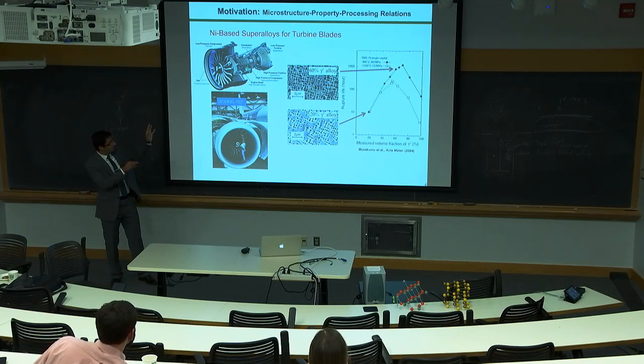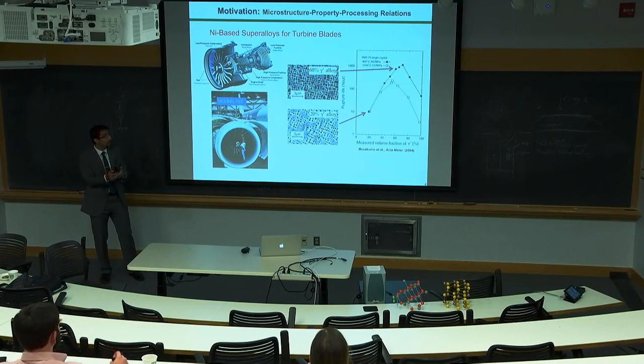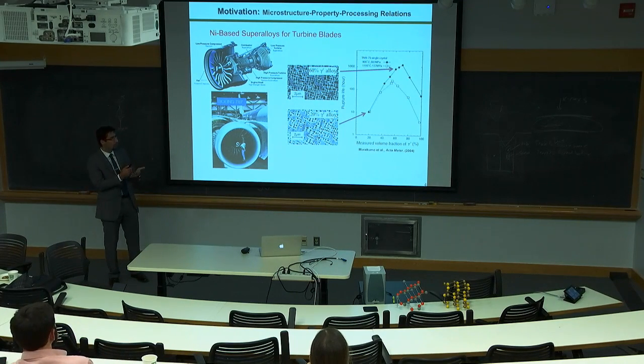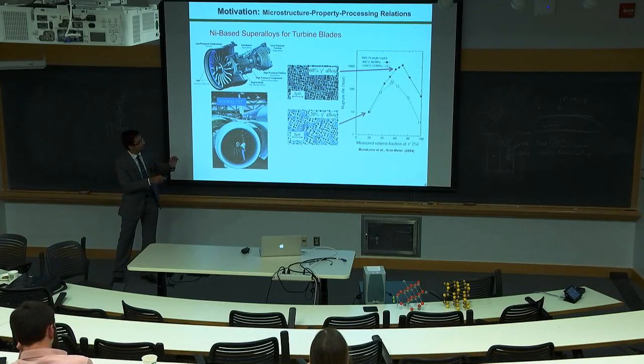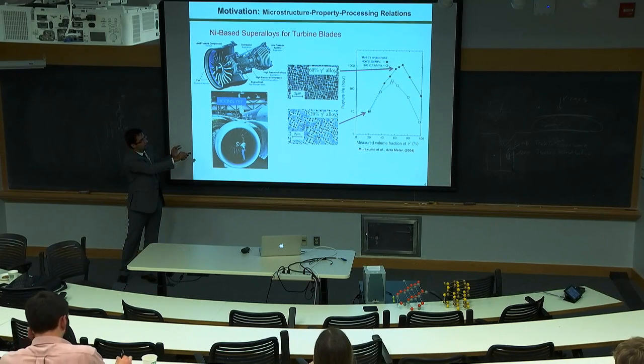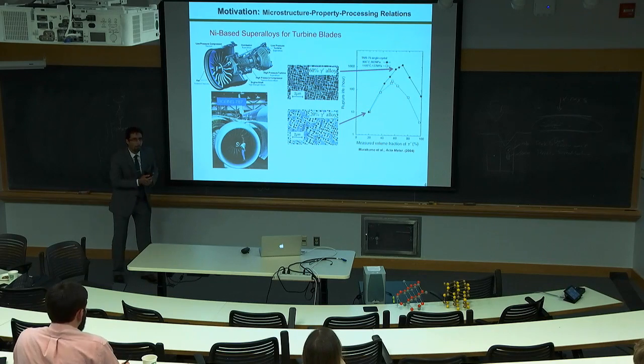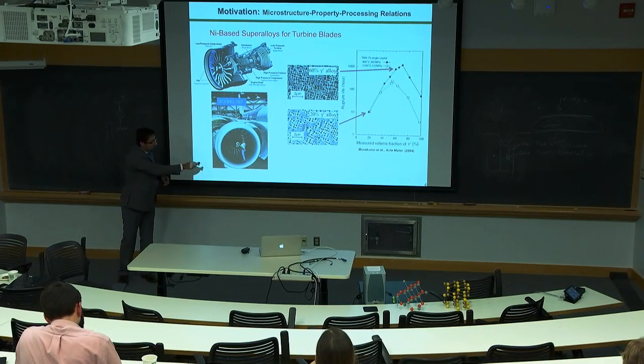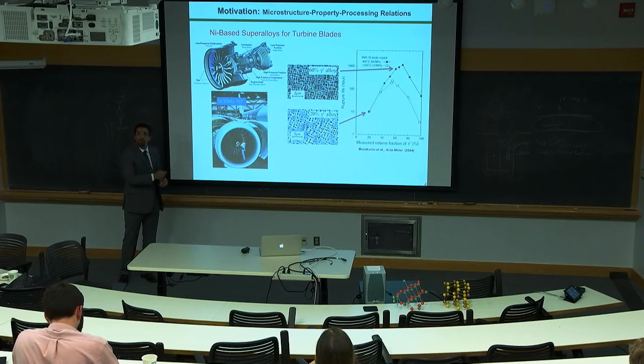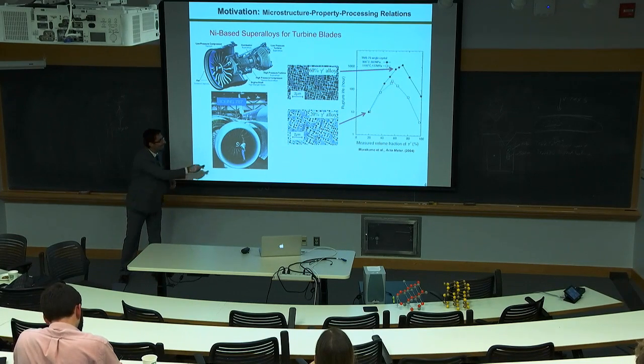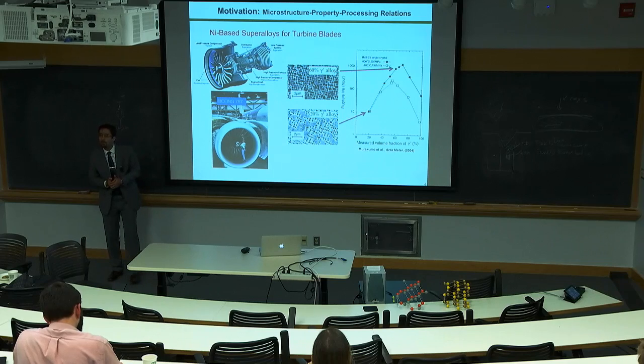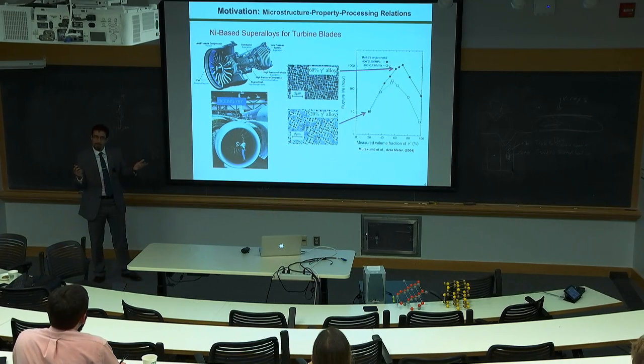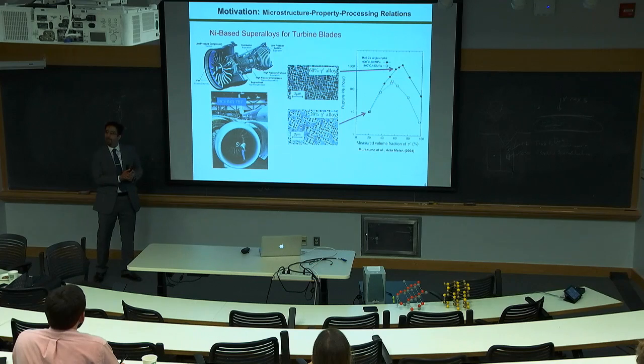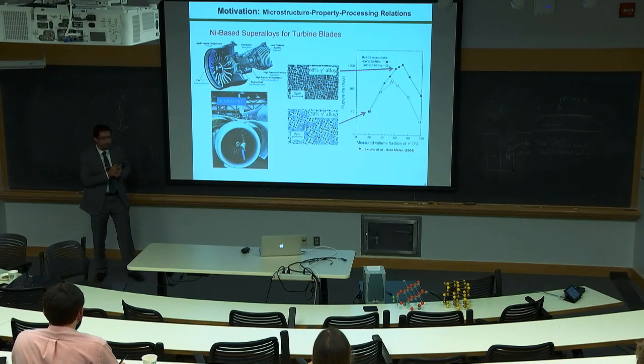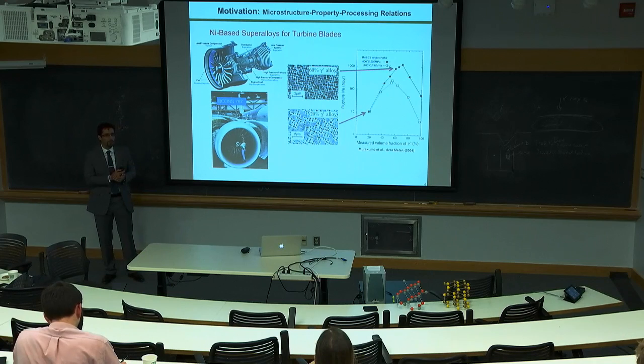When a jet engine is in takeoff, it can get to a very critical temperature. And sometimes it will remain at that temperature, which is going to be a very critical situation. So let's assume that the jet engine reaches 900 degrees Celsius, these black dots here. If we use this nickel-based superalloy to make the turbine blade, the jet engine will only last 10 hours. So if you're on a flight going from Boston to Beijing, it's more than 10 hours, right? And this happens in the beginning. The pilot can monitor the temperature, so he has to land before reaching Beijing.